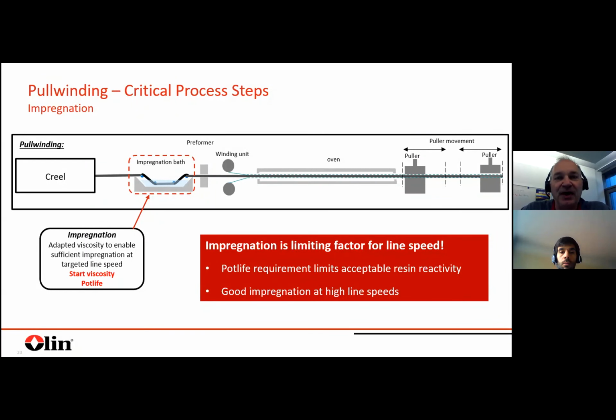So, and this is mainly, I often say we need a high reactive system to run the line fast. Yes. So it's for us not really a problem to create a high reactive resin system. So we can make it as fast as you want. The problem is really then the processability. And in the setup of a typical pullwinding line, it's an impregnation unit, it's a bath. So that means you have pot life requirements. And this is really a limiting factor for the resin reactivity of epoxy systems.